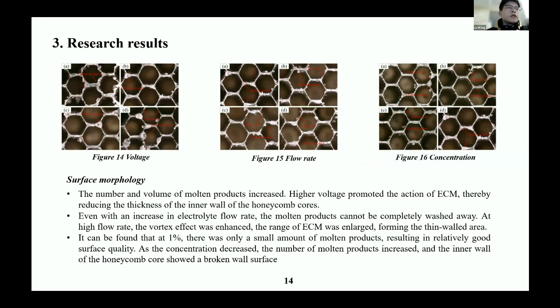The surface morphology after the processing is shown in Figures 14 to 16. As the voltage increases, the height of the molten product gradually increases, and the inner wall of the honeycomb cores also gradually becomes thinner. However, an increase in flow rate cannot wash away most of the molten products, but instead enhances the eddy current situation, causing the inner wall of the core to become thinner. As the concentration decreased, the amount of molten products increases, and the surface morphology is much worse than that at 1%.